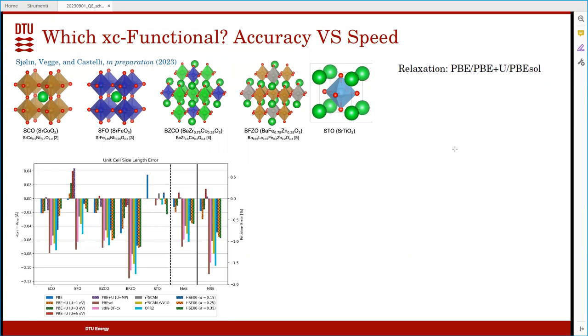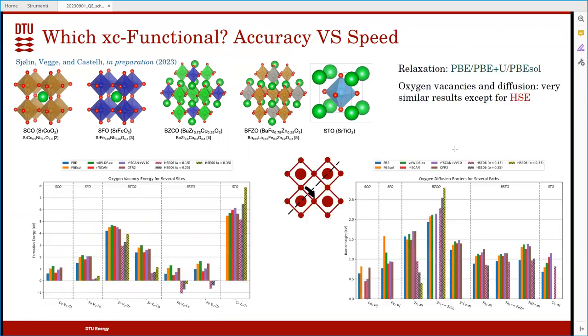When you do the relaxation, basically all PBE functionals work fairly okay. You can see that here they work within a 1% error, that is fine. That is more like what they want. It becomes a bit more tricky when you look at vacancies. We have very similar results for most of the GGA functionals. HSE behaves a little bit differently. We don't know yet why.